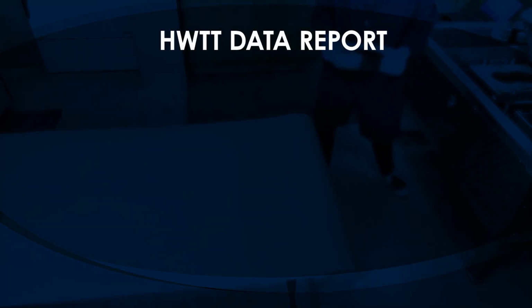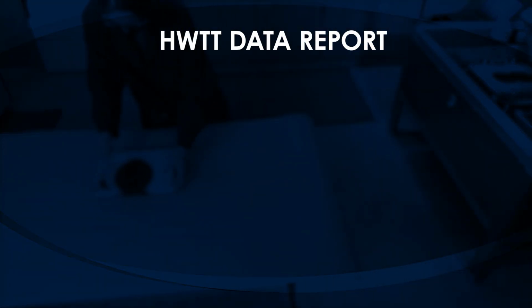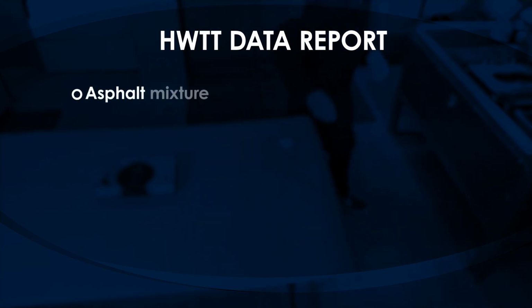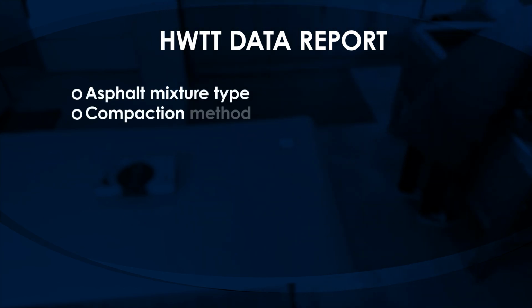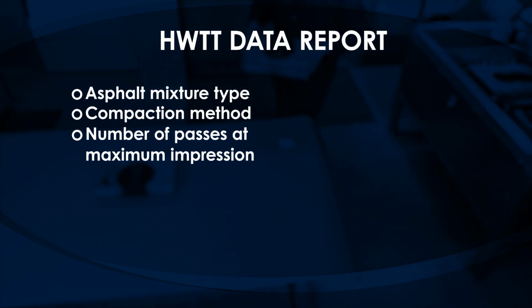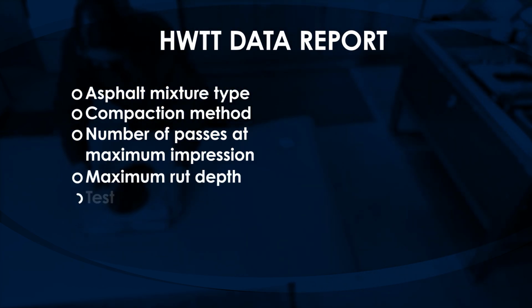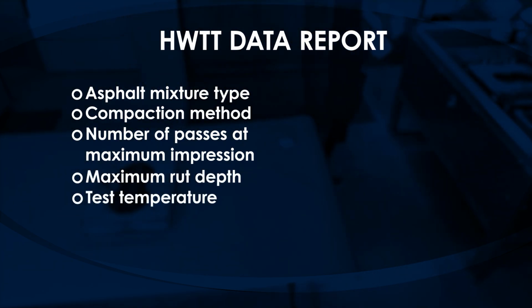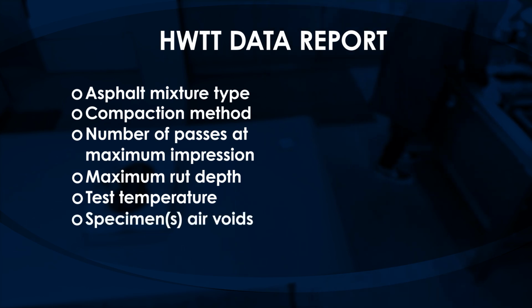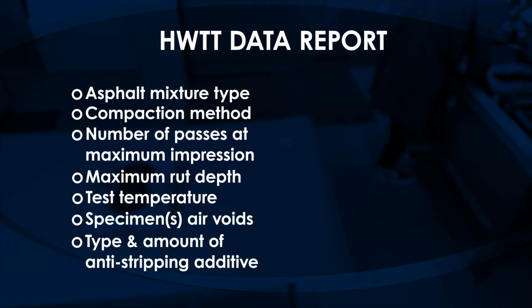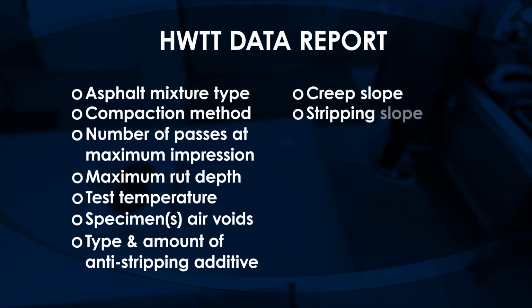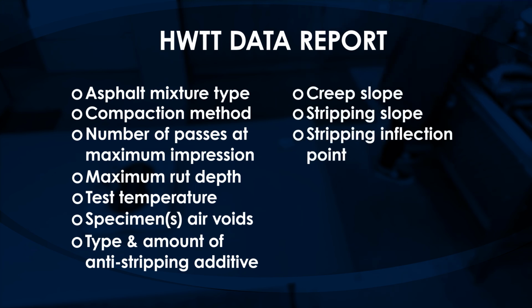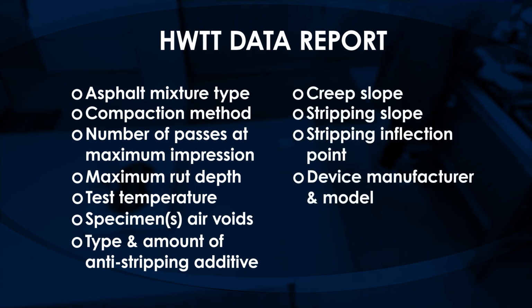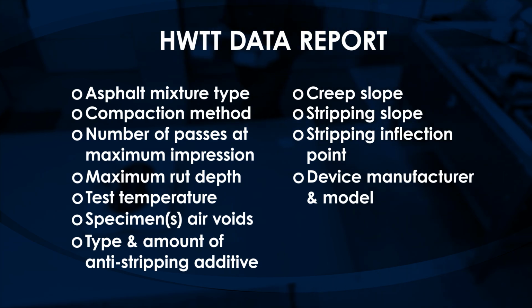A Hamburg Wheel track test data report may include the following parameters: asphalt mixture type, compaction method if applicable, number of passes at maximum impression, maximum rut depth, test temperature, specimen air voids, type and amount of anti-stripping additive used, creep slope, stripping slope, stripping inflection point, and device manufacturer and model.